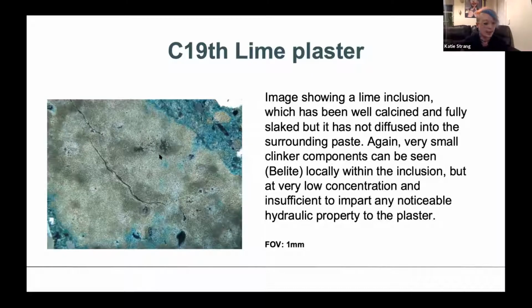Belite, when you're looking under a microscope, quite typically forms a kind of grape-like structure, and that's normally how people would identify it. But again, it's very low concentration, so this probably isn't having much of an effect on your mortar overall.